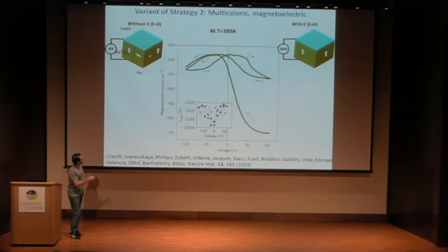We can control the magnetization as a function of the voltage, the electric field applied directly on the BTO ferroelectric. You apply the electric field on BTO, you induce some strain at the interface, and then you modify the magnetic state of the iron rhodium. So we have a very strong magnetoelectric coupling.